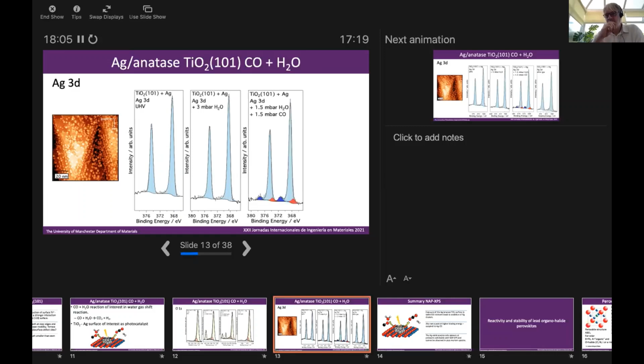However, when we add in the CO, the carbon monoxide, we do see some significant changes in this silver 3d spectrum. The first thing we see are these two red peaks. These are the spin orbit split doublet, which corresponds to the main silver 3d peaks. And we also get these two blue peaks. So the red peaks here are due to oxidation of the silver.